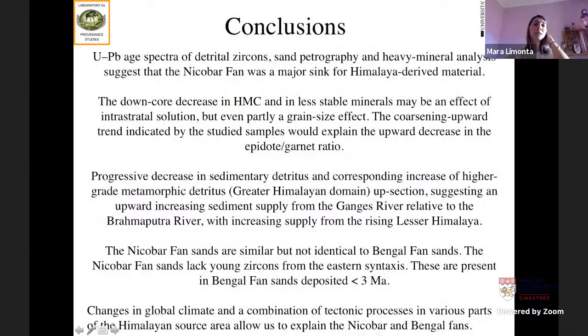So to conclude, we can say that all this mineralogical composition and geochronological composition suggest that the Nicobar Fan was a major sink for Himalayan-derived material. The downcore decrease in heavy minerals and the less stable minerals may be an effect of intrastratal dissolution, but also a grain size effect. So the progressive decrease in sedimentary detritus and corresponding increase of higher grade metamorphic detritus suggests an increasing supply from the Ganga River relative to the Brahmaputra.